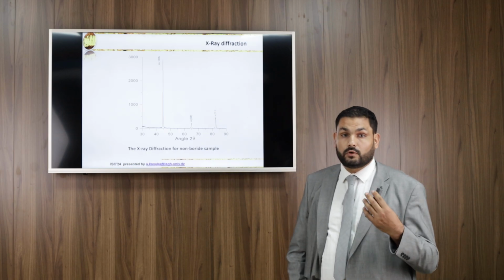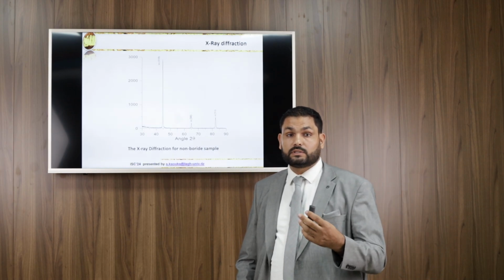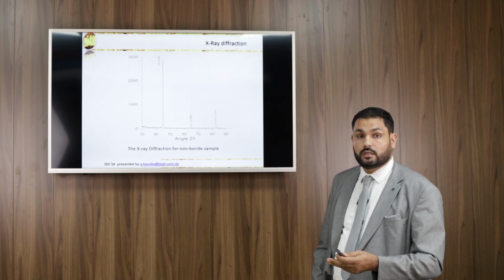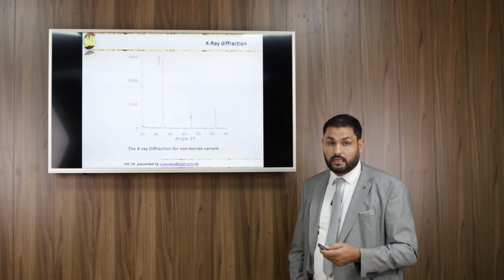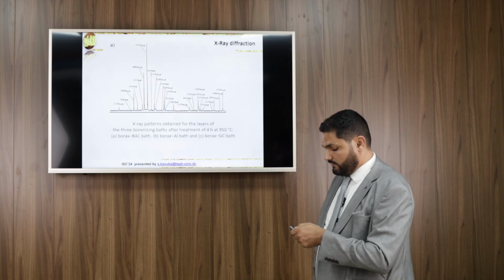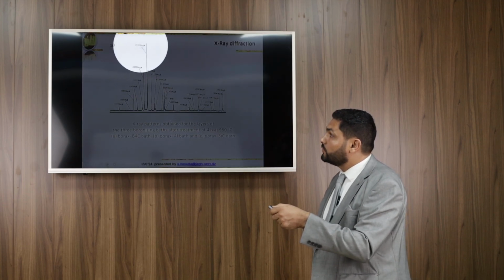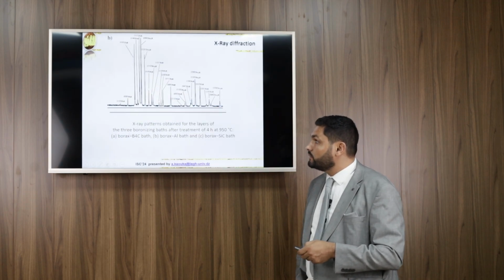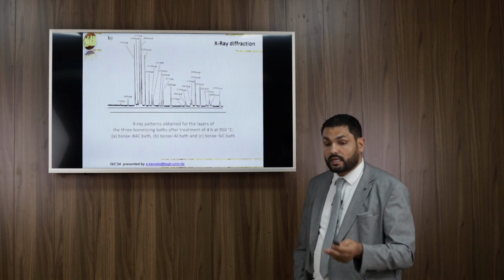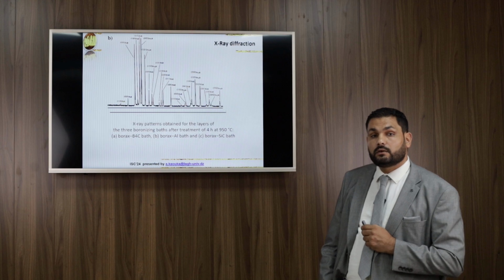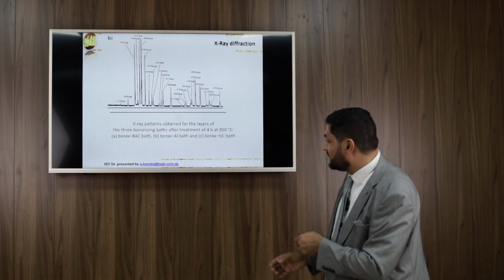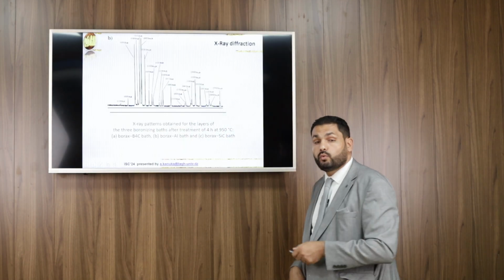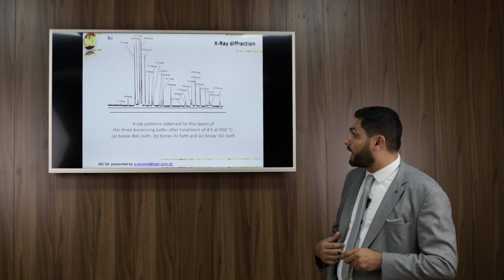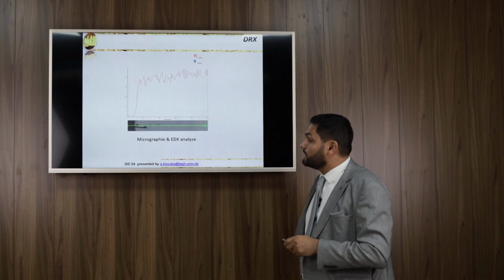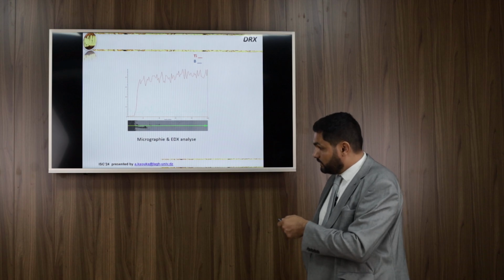In a previous study for iron or carbon steel, before treatment we have alpha iron, and after the boriding treatment we have Fe2B and FeB, processed in 3 baths: borax with boron carbide, borax with aluminum, and borax with silicon carbide. We will see that with silicon carbide, we have only a monophase, only FeB.